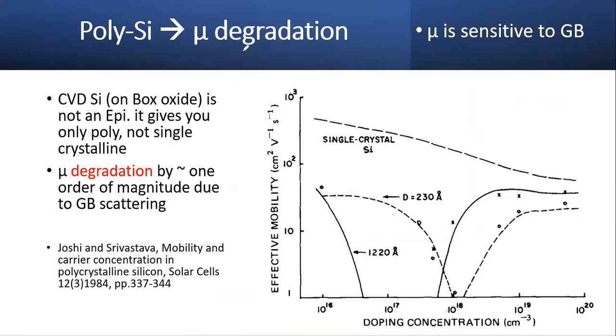The reason is that polysilicon has a very bad mobility. You can look at this curve on the right-hand side. Forget about the different doping. For low doping, you can see that it dropped. Compared to single crystal, the mobility of carriers dropped by 1 order of magnitude from here to here. It doesn't matter what doping concentration, it dropped pretty dramatically. And D here is the grain size, different grain sizes. No matter what you do, the small grain size, the large grain size, they all drop by 1 order of magnitude. So that's a problem.